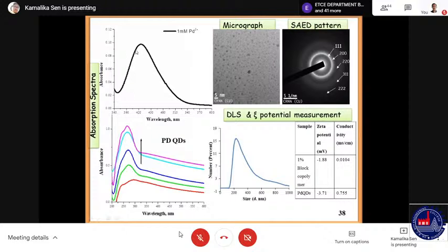Absorption spectra of palladium 2 plus solution shows a peak at 420 nanometer, and after palladium quantum dot formation, we can see that there is no particular surface plasmon resonance in the visible region. This observation was also observed in our earlier work. So we can see that the palladium quantum dots have been formed with 2 to 3 nanometer size particles.